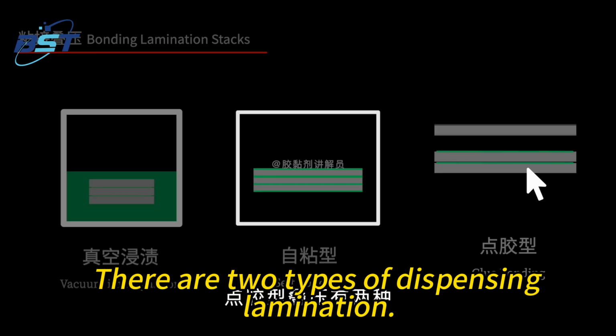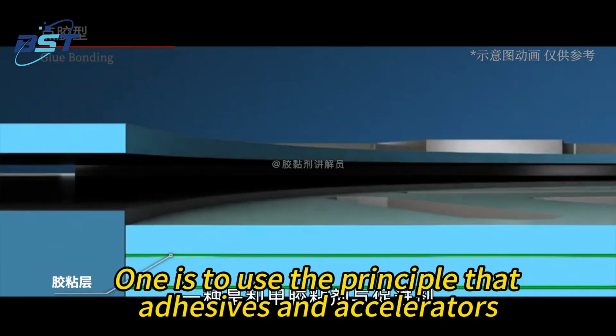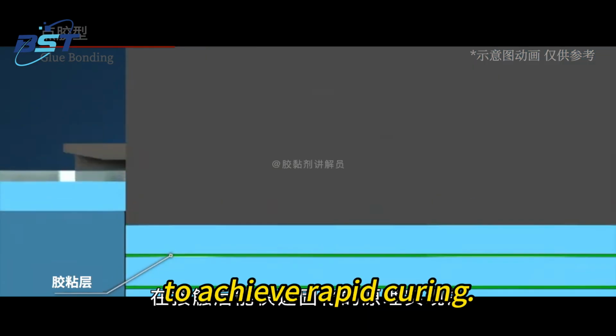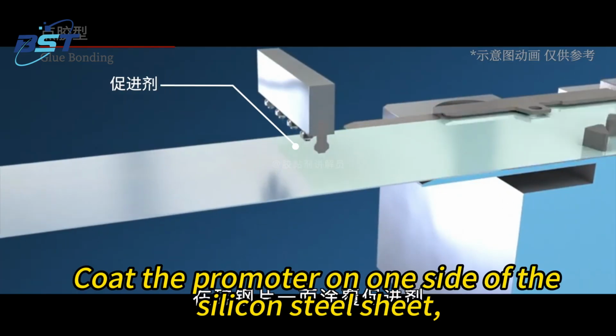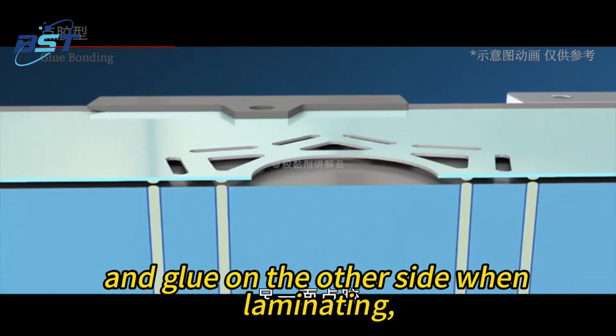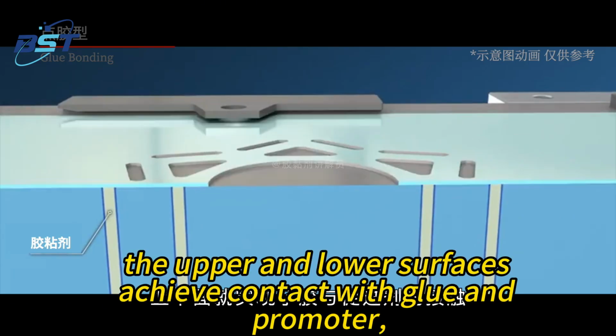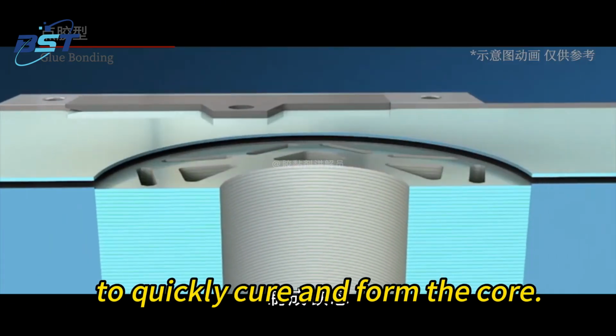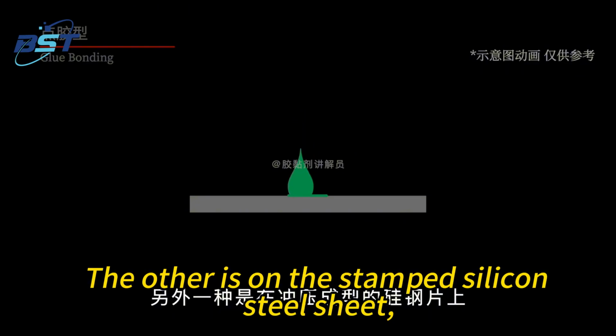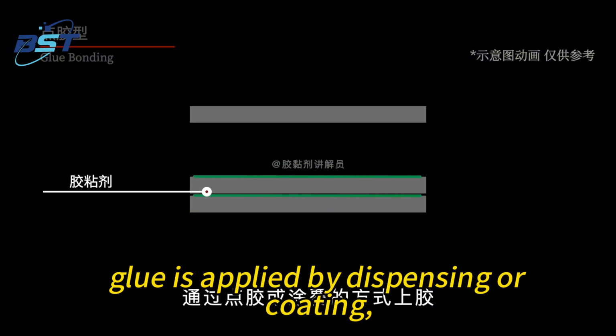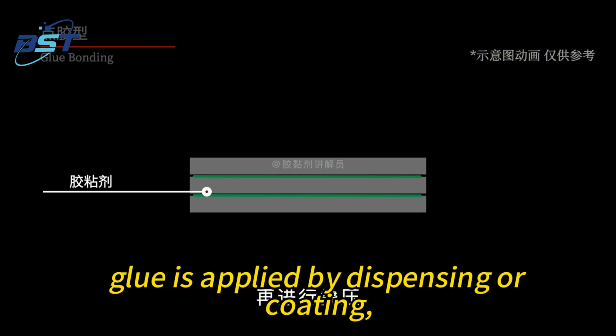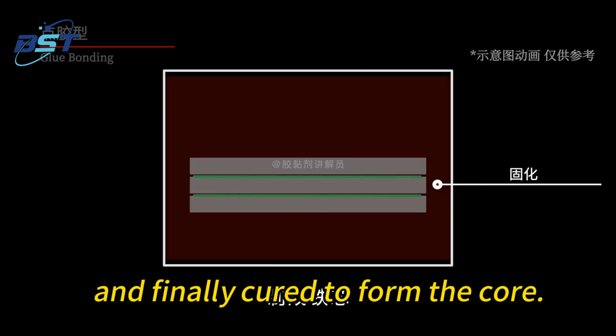There are two types of dispensing lamination. One is to use the principle of adhesives and accelerators to achieve rapid curing: coat the accelerator on one side of the silicon steel sheet and glue on the other side when laminating. The upper and lower surfaces come into contact with glue and accelerator to quickly cure and form the core. The other is that on the stamped silicon steel sheet, glue is applied by dispensing or coating, then laminated, and finally cured to form the core.